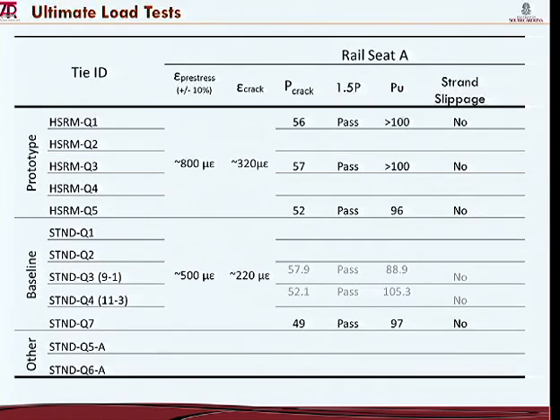Now, when we drove the test to failure, for the prototype ties, the pre-stressing strain is approximately 800 microstrains, 760, 770. And the crack is computed based on the flexural strength to about 320 microstrains, whereas for the baseline, 500 microstrain pre-stressing and 220 microstrain for the crack flexural strength. So in order to crack the specimen, we need to monitor strains for the HSRM above 1100 and for the baseline above 700. Okay? Because remember, the DIC assumes a zero position when the pre-stressing is already applied. So whatever may be monitored or recorded as tension in the DIC, it's not really tension. We have to add the compressive stresses due to pre-stressing there.